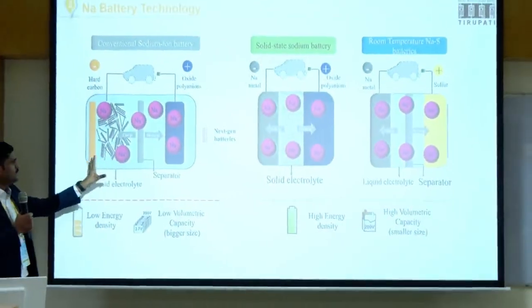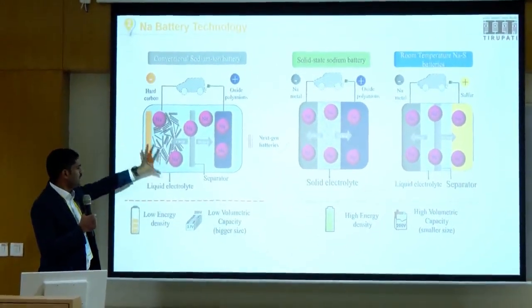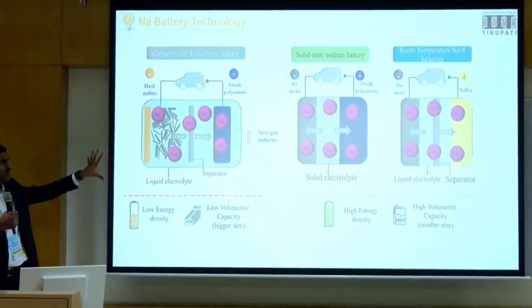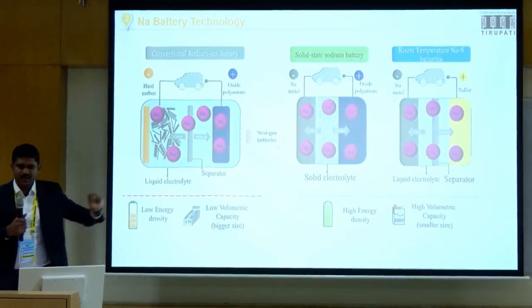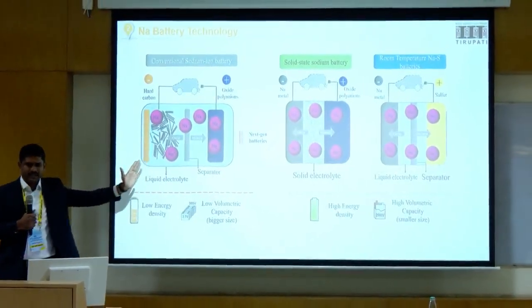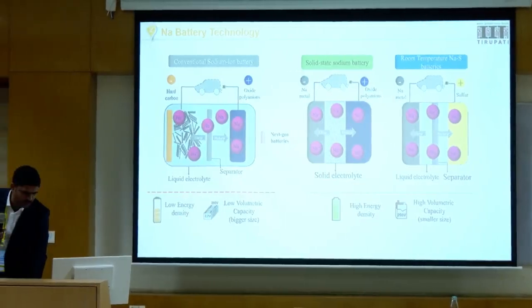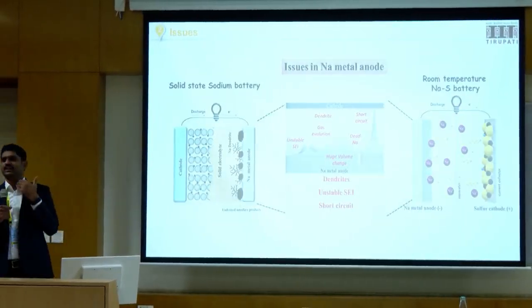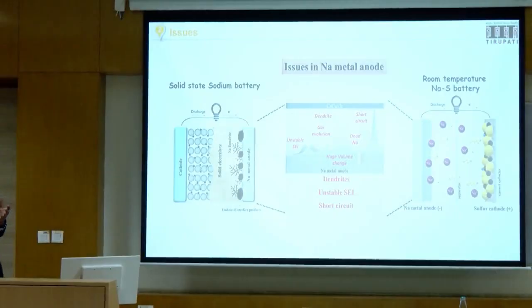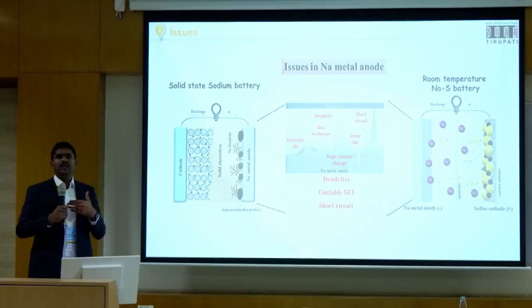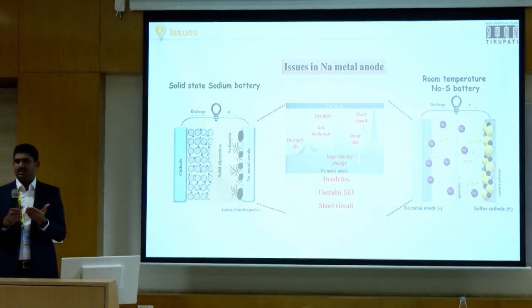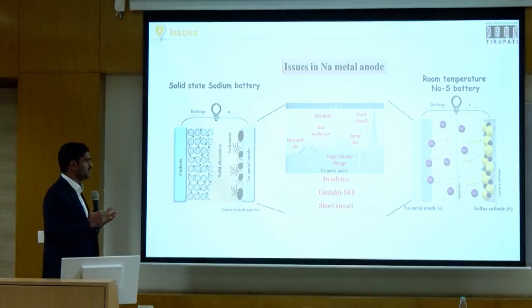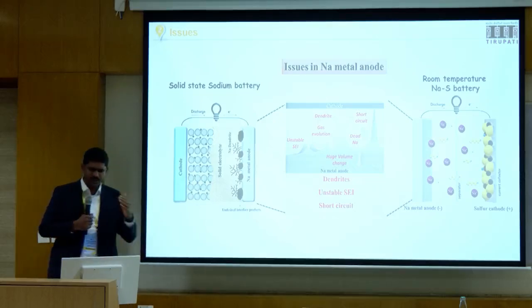Okay, so there are different types of sodium-ion battery technology. This is a conventional sodium-ion battery technology where sodium ion moves between anode and cathode. They generally have carbon-based anodes. The idea is to replace the carbon-based anodes with sodium metal directly, so that you can develop a high energy density sodium-ion battery technology with energy density nearly equivalent to or much higher than lithium-ion battery technology. But however, as I said, metal anodes have a lot of issues, in particular the dendrite issue.